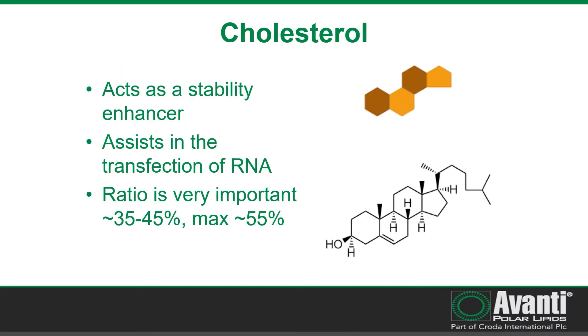Let's start with cholesterol. Cholesterol plays an important role in most lipid particle systems and nucleic acid LNPs are no different. Cholesterol acts as a stability enhancer by filling gaps in the lipid layer, and it has also been shown to assist in transfection. Marketed products currently have a cholesterol content between 35 and 45 percent. Cholesterol must be present to have an effective delivery vesicle, but its ratio is very important as too much cholesterol can prevent particle formation.